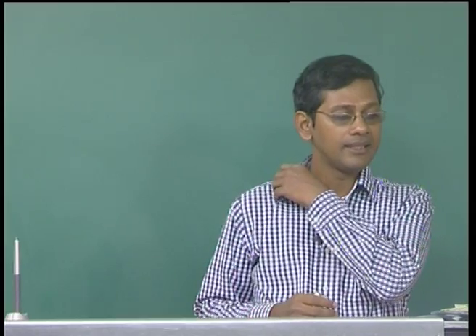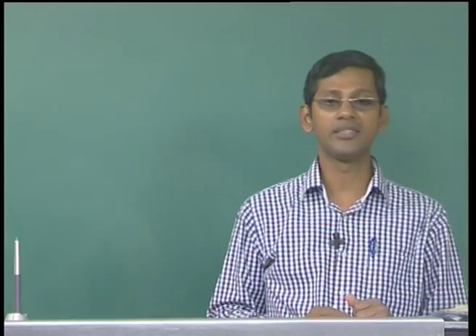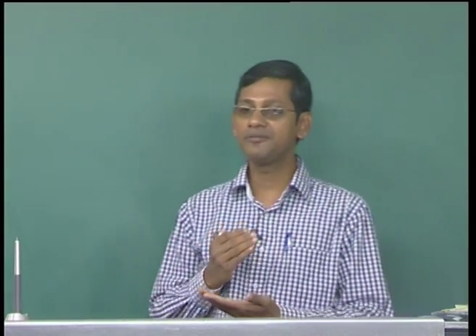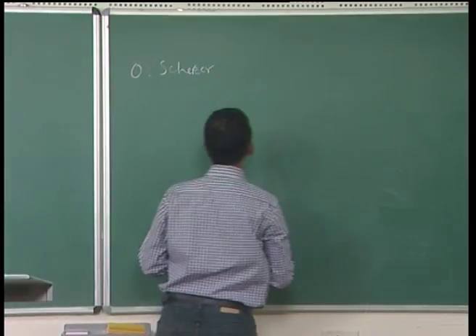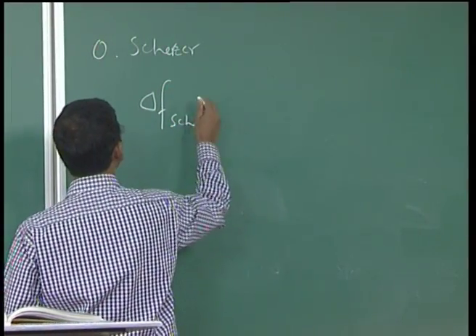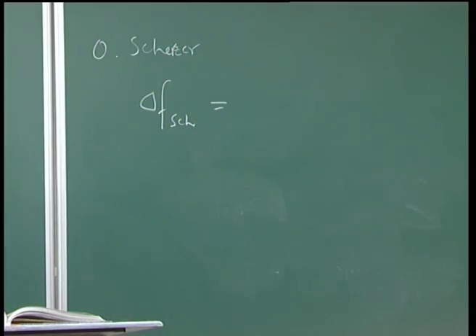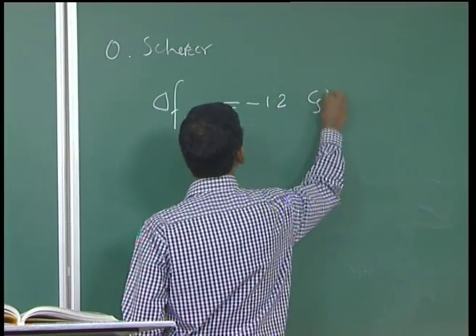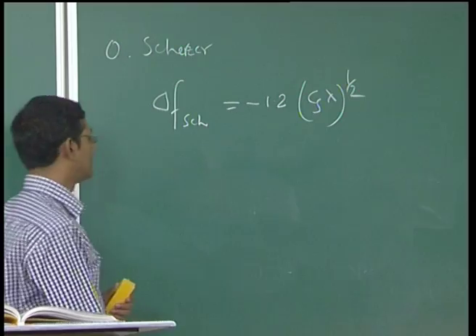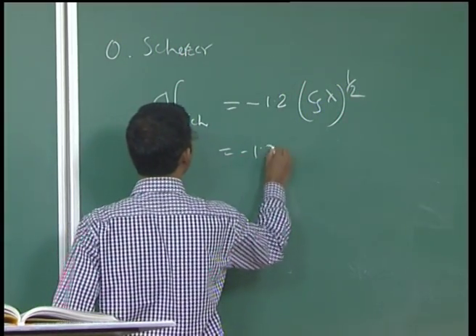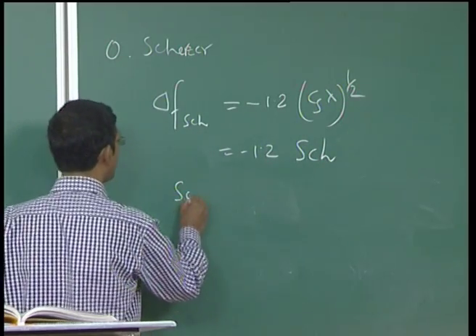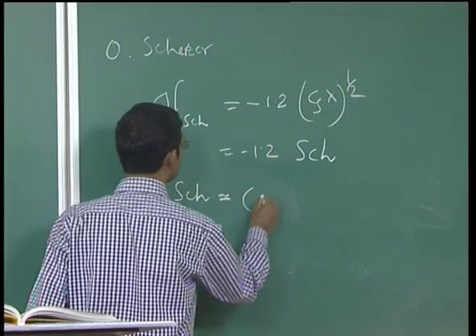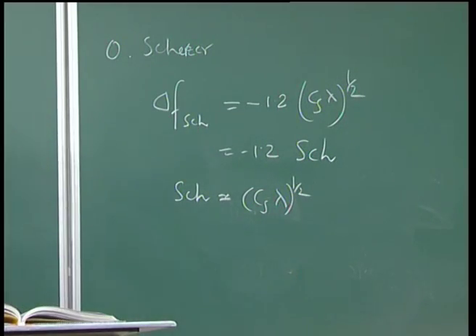What he said is that the transfer function can be optimized by balancing the effect of spherical aberration against a particular value of defocus. So I need to get a particular value of defocus where the effect of CS can be balanced. This delta f is known as the Scherzer defocus, which is given by this formula: minus 1.2 times CS lambda to the power half. And many times we write this equation as minus 1.2 SCZ, where SCZ is the Scherzer defocus, CS lambda to the power half.